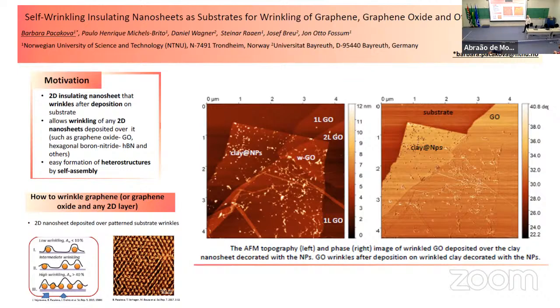That's one thing we have achieved. So these are AFM images showing how we can control graphene wrinkling by depositing graphene on top of clay sheets where we have controlled the wrinkling. So we are depositing graphene oxide on top of clay with controlled wrinkling, and then the graphene follows that wrinkling.